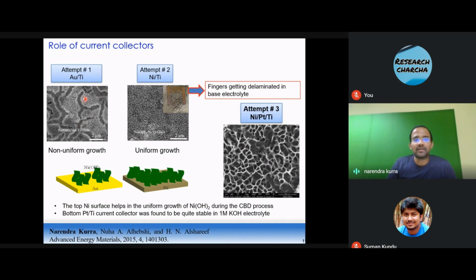When we started doing chemical bath deposition, we didn't observe uniform, homogeneous deposition of nickel hydroxide on top of gold. This could be due to the difference in the surface energies of the two materials. And we thought, let's take nickel as a top layer in place of gold. When we have nickel, we see homogeneous growth of nickel hydroxide petals, as shown here.